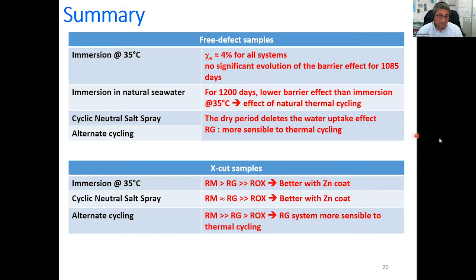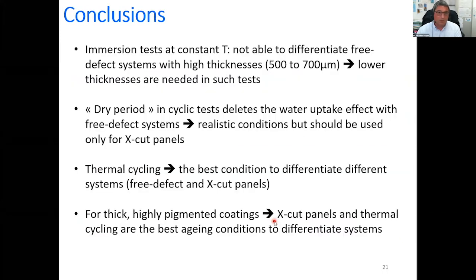Now for X-cut samples, the immersion at 35 degrees C showed that the RM system was the best one. Same thing for the cyclic neutral salt spray. It is better with the zinc coat. But more importantly, the alternate cycling was the only test that was able to differentiate between RM and RG systems, with again the conclusion that the RG system was more sensitive to thermal cycling.